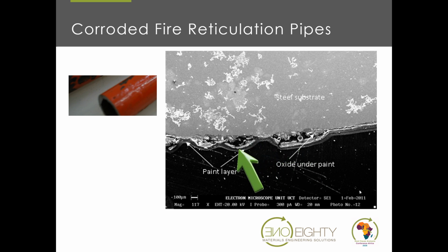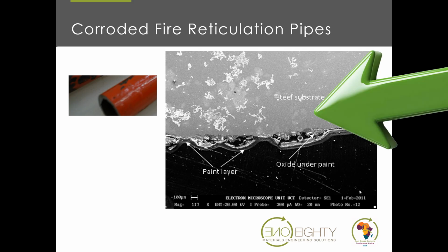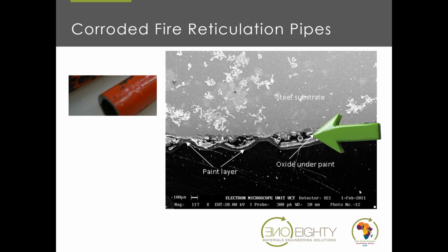This over here is rust. The electron microscope also allows us to put the probe into the areas of interest and measure the elements that are present there. So we were able to confirm by first testing with a probe what was here in terms of the steel, and then putting the probe onto this contaminant here and seeing a change in iron levels and manganese levels, and we could conclude that that contaminant there was rust.